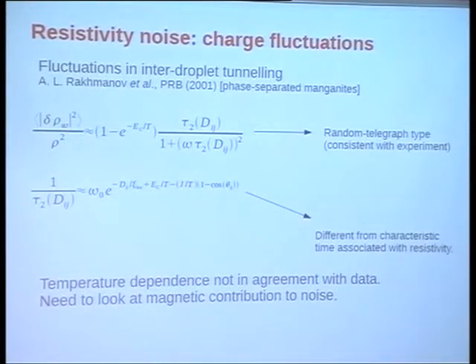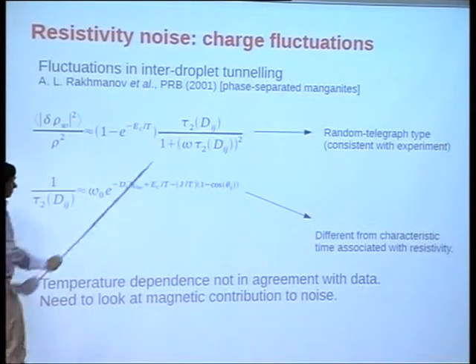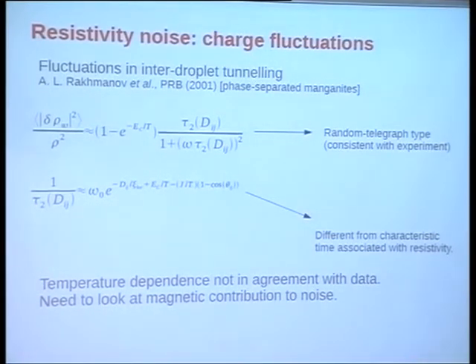Okay, so what causes this noise? We have analyzed 2 possible sources. One is the fluctuation of charge in these puddles itself, and the other one is fluctuations of orientations of magnetization. The fluctuation of charge has been studied in other contexts, like in manganites, where you also can have charge inhomogeneities, and the resistivity noise can be worked out. It gives you a kind of telegraph noise with a characteristic scale determined by activation energies, the ordering, as well as attempt frequency of getting out of the puddles, localization length, all sorts of things.